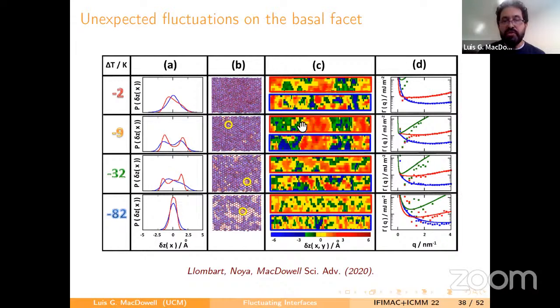And you can see this in the contour plots. You can see clear patches of domains with different height. But surprisingly, if you keep increasing the temperature, then this bimodal distribution vanishes and you get a Gaussian distribution again. So what this means is that the basal facet of ice has three different phases: one smooth, low temperature phase, one rough, intermediate temperature phase, and then a smooth phase again. And this is going to change how the crystal grows and the speed of growth.